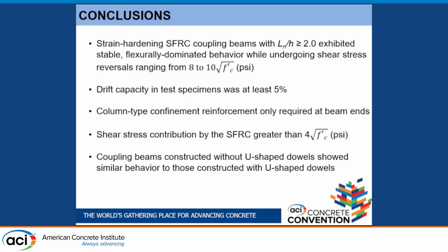As I just mentioned, we can rely on a contribution of the fiber concrete to shear, the so-called V sub C term, for use in the middle regions of the coupling beam, which was 4 root of F prime C.